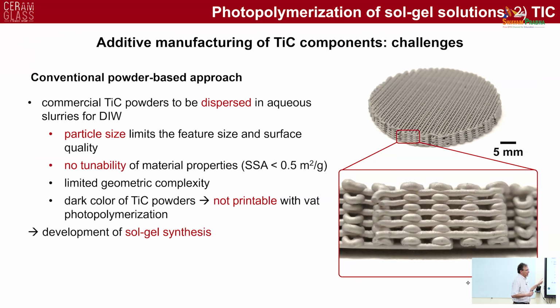And by the way, the system is now running. They're not yet using our targets. They're using commercially available silicon carbide discs that have some limitations in terms of the ability to release the isotopes, but they wanted us to do titanium carbide. And you can buy titanium carbide powders. You can make discs that are required as target. The target is actually comprised of a series of discs, seven discs of this size, and the thickness is about 1 centimeter.